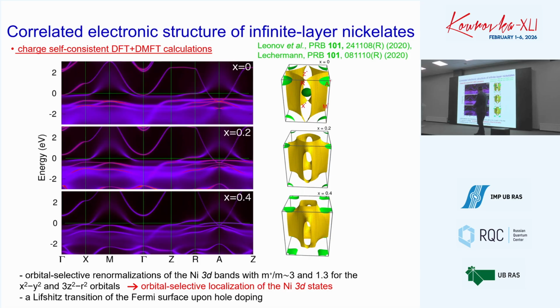These are the Fermi surfaces, and this paper was essentially published together with our next speaker, Sergey Skornyakov. We do see a change, a Lifshitz transition, and two orbitals are involved: the planar x squared minus y squared and z squared orbitals. They show strong orbital selectivity with strong renormalizations, which differ by about a factor of 3. We do see a clear Lifshitz transition of the Fermi surface, possibly associated, as I will show in the next slides, with the construction of magnetic correlations.